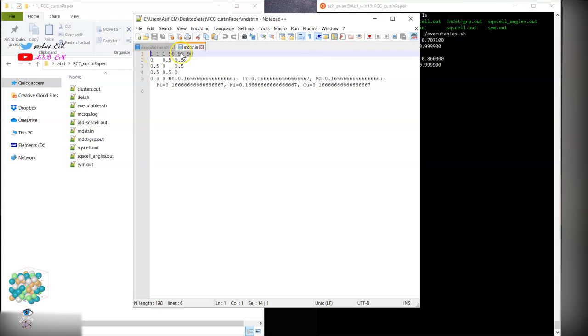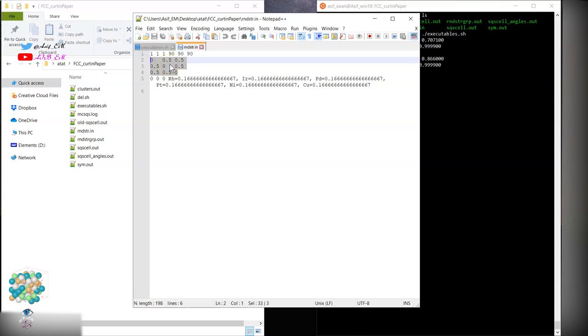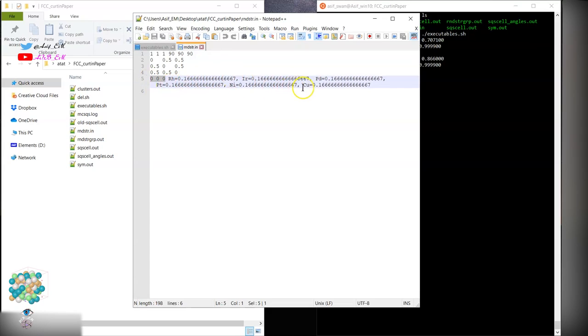These are the Cartesian coordinates or the orthogonal space. The rest three are the lattice vectors which are the primitive vectors. It's best to use the primitive vectors because SQS will explore whole space containing multiples of this one. And for FCC, we have one atom with this composition equimolar.